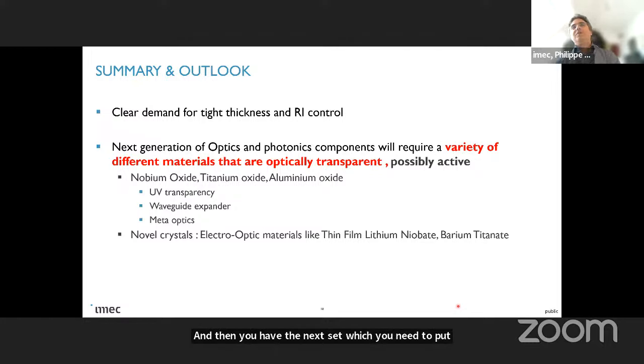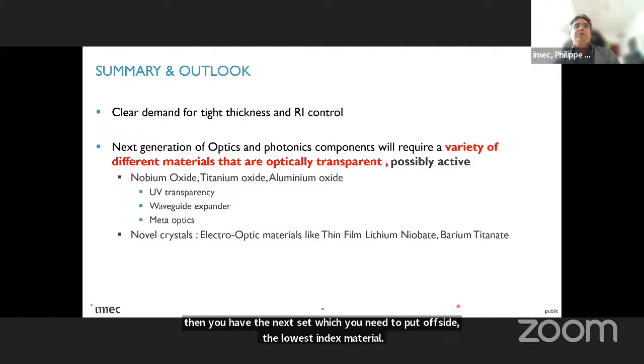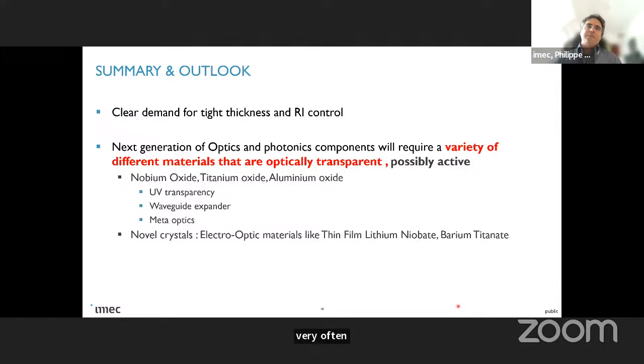And that oxide, it's not very often cited, but sometimes induces optical losses as well, because the people that work on these depositions add their ingredients, the precursors and so on that are typically used in CVD processes, and they also induce losses. Niobium oxide and titanium oxide are very important for us for the upcoming platform. We have demonstrated niobium oxide as a waveguide. So the losses are not yet at the level of what we can reach with silicon nitride, but are today maybe in the range of what you can do with crystalline silicon.